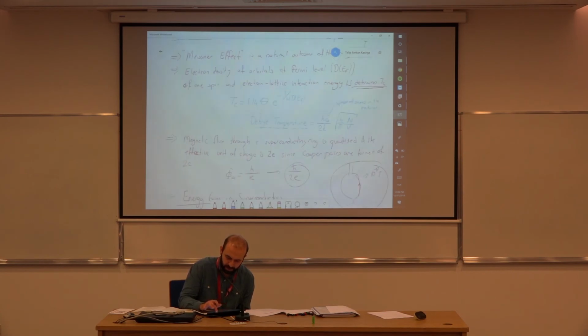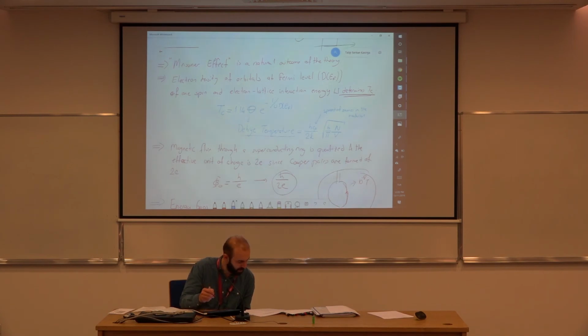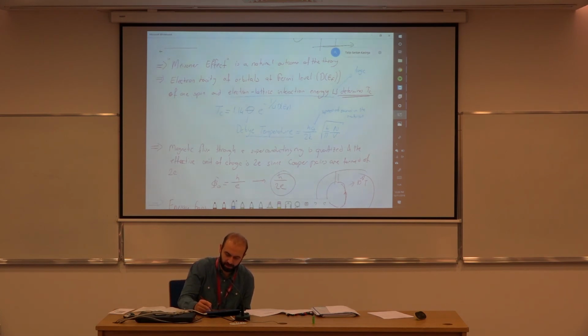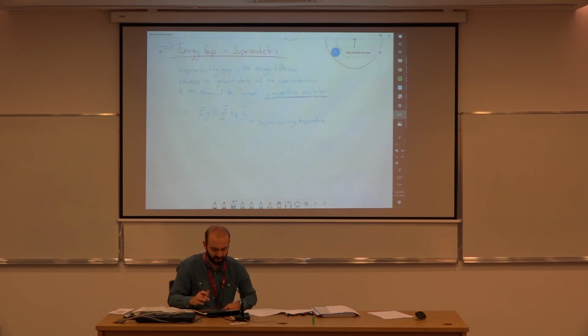One thing that I forgot to mention in our discussion here is that this electron lattice interaction energy, if it is large at any temperature, then this leads to a larger resistivity when the material is in its normal state. But ironically, when you have large U, then this exponential factor will be lower. Thus, this factor will be higher, so you'll have higher Tc. So the more resistive or the worse metal you have will have the higher Tc, so it will become superconducting sooner. That's sort of ironic. So it lives its normal life as a resistive material and then it becomes superconducting sooner.